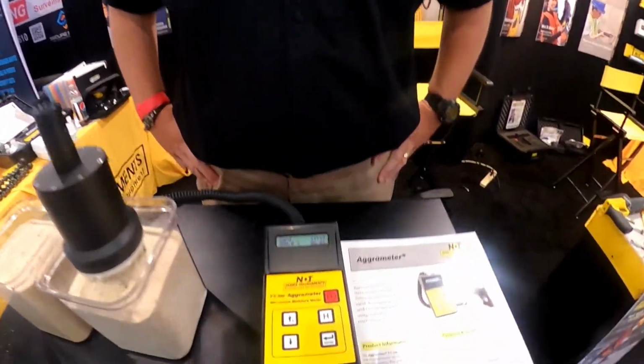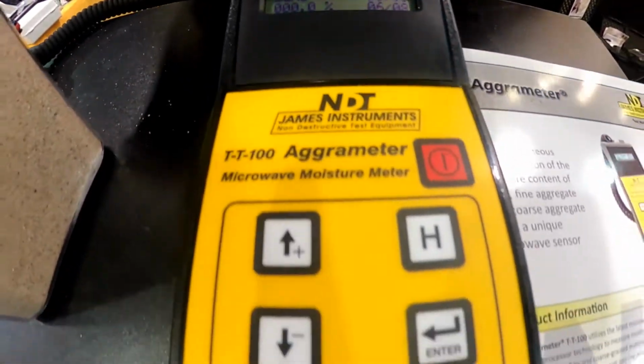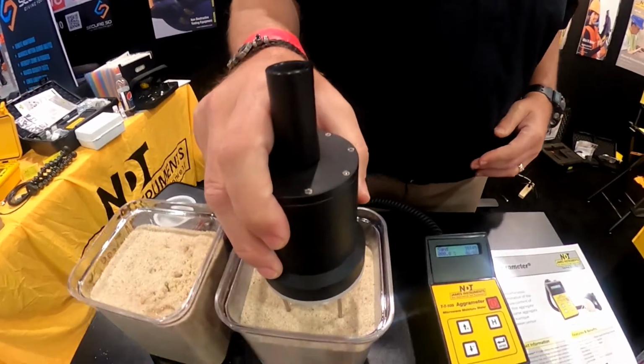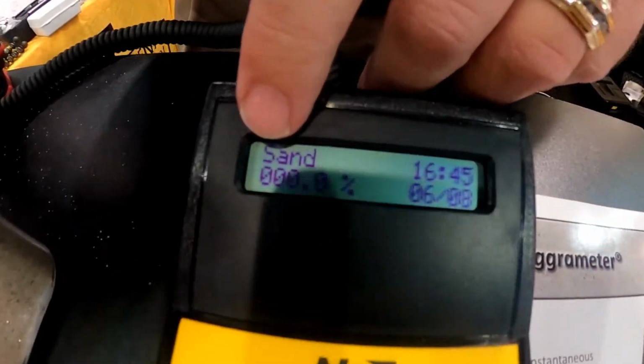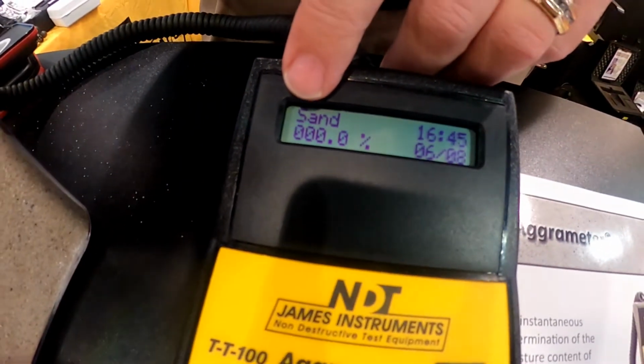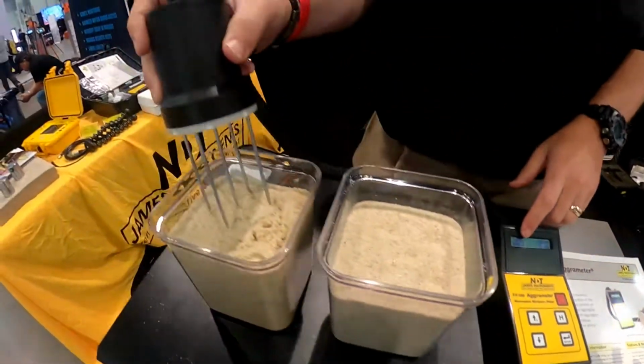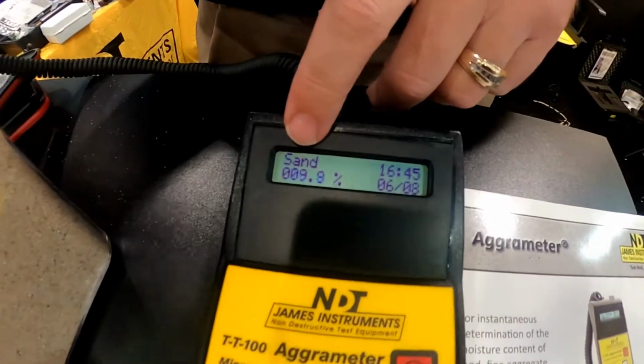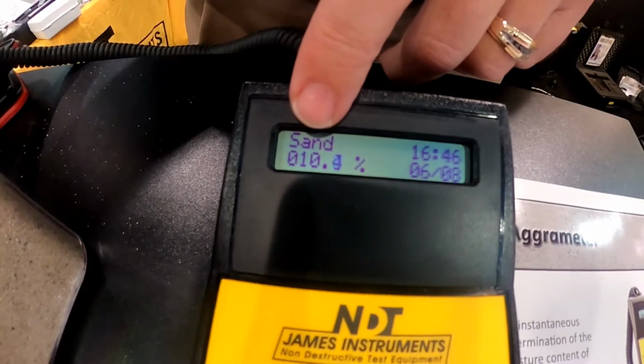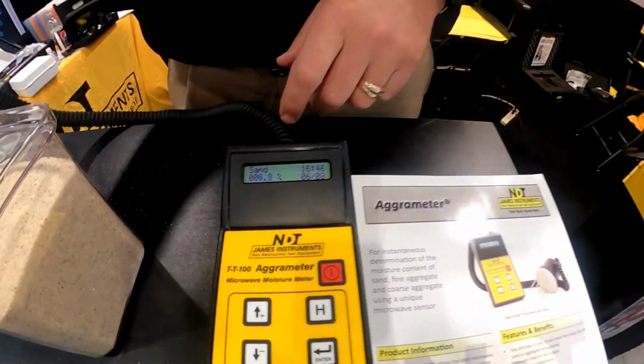This is another product we get a lot of interest in here at the World of Concrete, the Aggrameter for the measurement of moisture, sand, and aggregates. It uses this microwave sensor, and you insert these prongs into the material under test, and it'll read out the percentage moisture. So this being Las Vegas, the sand is pretty dry, and we're reading 0%, which is not that interesting. Later, when we now put it in the other sand, we get a reading of 9.8%, let's say. A little bit of variation because we've been testing all day. The unit can store up to a couple thousand readings. You can program it with your own materials. It can test sand and any aggregate up to a 3/8 of an inch maximum diameter of the aggregate.